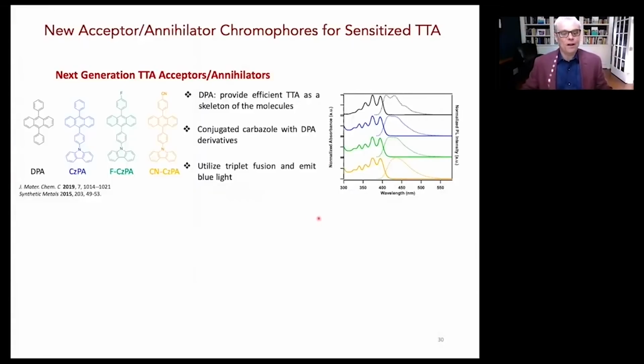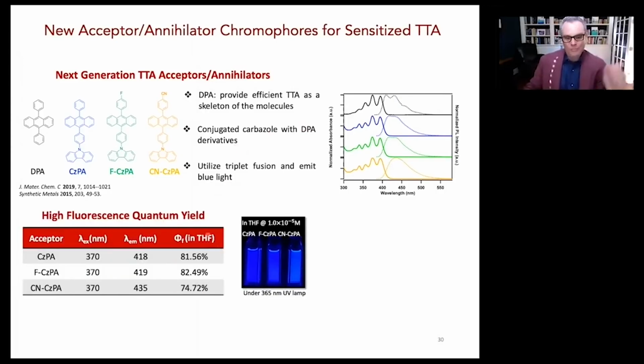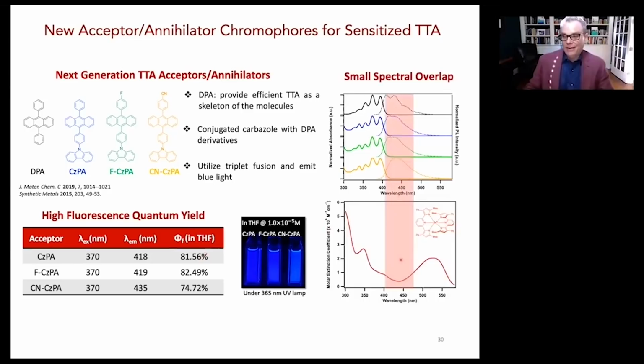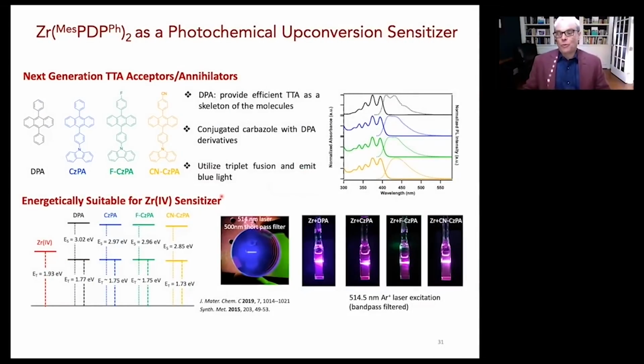But we decided, let's do this a little bit differently. Let's now make a lot of different diphenylanthracene derivatives and see if we can do anything better than diphenylanthracene married to this particular sensitizer. And as you can see here, we get kind of similar fluorescence properties in all of them. We have an absolute quantum yield apparatus, so these are all really high fluorescence quantum yields. They're all beautifully blue again. And the idea is the emission bands of all of these molecules fit into effectively the main depression in the absorption band from the zirconium photosensitizer. So we felt that we can upconvert, and we won't have really any major problems with inner filter effects. So that's what we did.